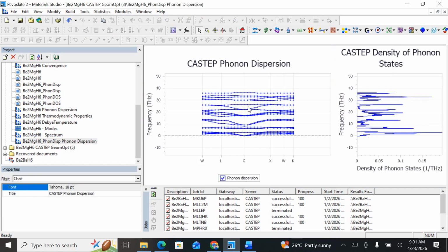And there is also one other rule. We have a well-known formula, which is 3n, and these lines should follow the 3n formula. For example, if we have a total of 9 atoms in a unit cell, and we put 9 in this 3n, we get 27. It means these lines should be 27, not more than or less than 27.